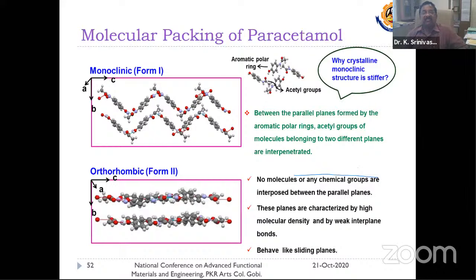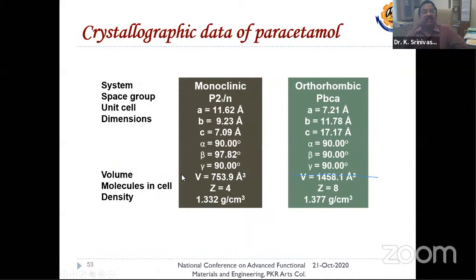But the problem here is that one has to struggle to nucleate this form too. It's not a simple task. After implementing various other techniques, we were successful in crystallizing this one. Some other researchers also found this one, but it's not stable. It is a metastable one. Of course, these are all the crystallographic differences. So monoclinic, these are all the crystallographic parameters, orthorhombic.